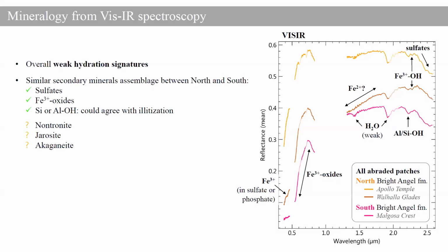Now, if we look at iron, we see the signature of a ferric oxide in the visible, and we also observe a very weak band at 2.28 microns, so an iron 3+ OH band that could be explained by nontronite, or perhaps jarosite, but it's a bit less convincing. And finally, we also had hints of a 2.46 micron band that could be indicative of akaganeite, which is an iron hydroxide.